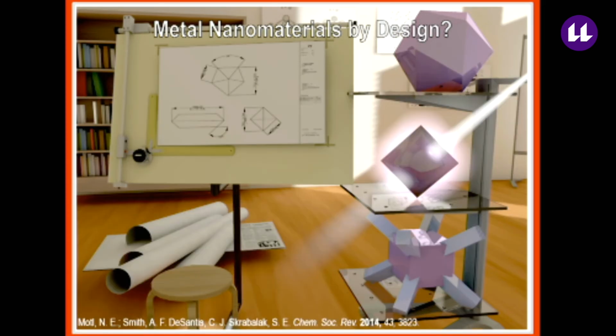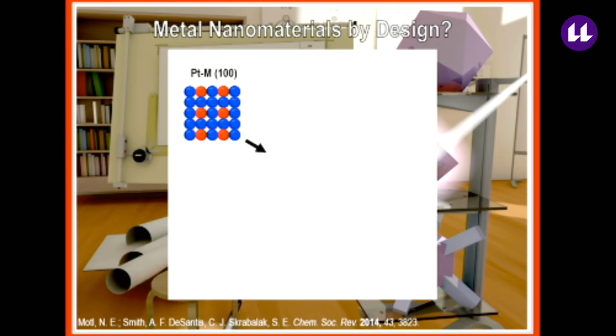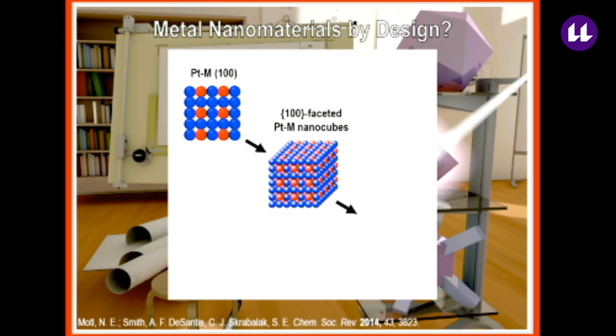Likewise, in the field of catalysis, you could imagine being inspired by some DFT simulations or some fundamental surface science studies that would identify a particular surface that's ideal for catalyzing a particular reaction. You can then develop a synthetic approach to express that surface in high percentage. And then maybe the activity or selectivity isn't perfect, but it's close. Then you can couple it with a seeded method, for example, to put that shell in compression or tension so that you can modulate its electronic structure and achieve efficient catalysis.